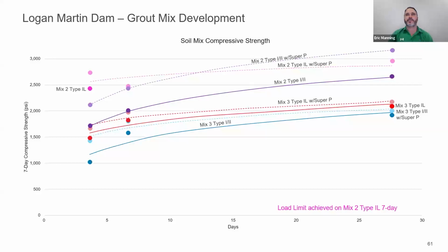This mix 3, type 1L, is the current mix with the super plasticizer, the Sika 300 super plasticizer, that we use with the clay mix. That's our current mix that we use for low mobility grout columns.